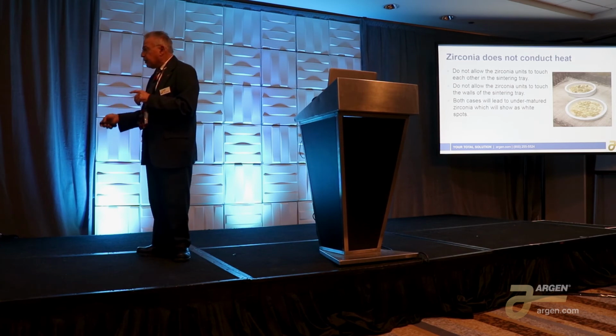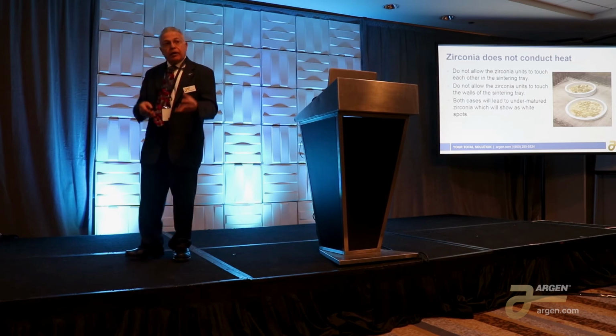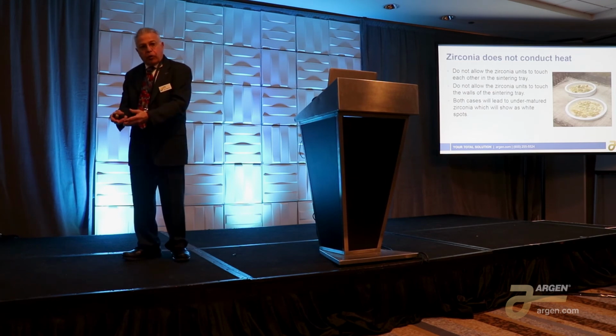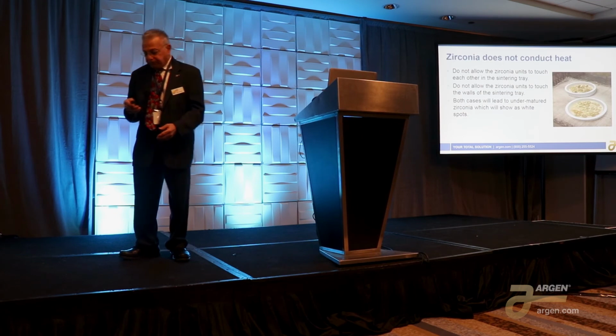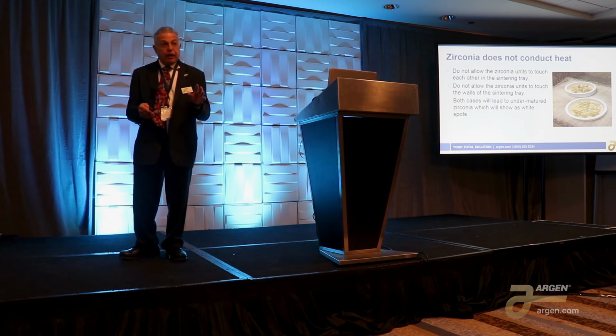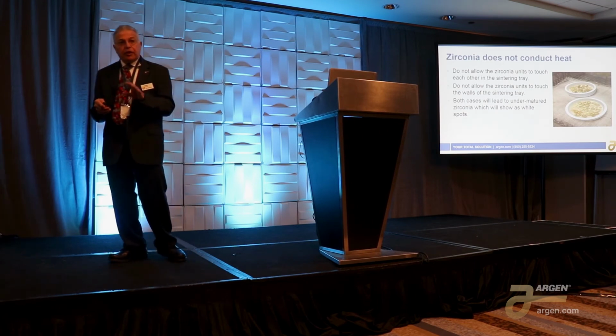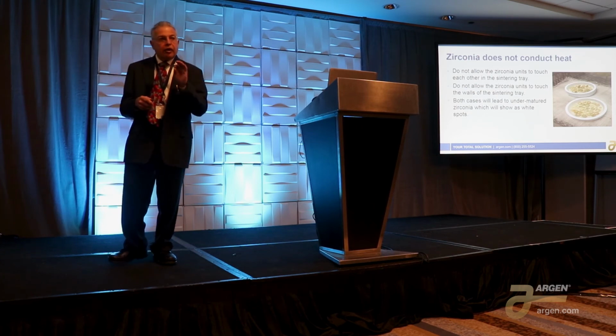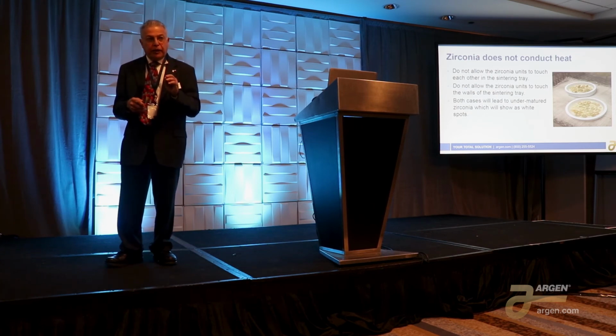So keep the little tray of extra beads next to your sintering oven, so that when it comes out of the sintering oven and it cools, you're able to see, okay, fine, now I need to change the beads. Again, it'll save you time. If you allow the units to touch each other or the beads get too dirty, you're going to start developing white spots on the zirconia.